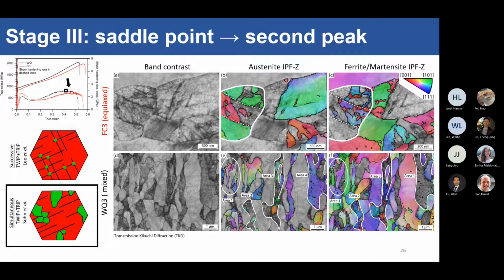So now let's take a look at the martensite. So this was the same sample at the second peak. But now this time using TKD to examine the microstructure. So in the FC steel, I've highlighted here this prior austenite grain with this annealing twin going across. And you can see that the martensite here actually nucleates off the grain boundary and then slowly grows its way into the grain interior. All right, so this is the hallmark of the simultaneous TWIP plus TRIP. Can you see that you've got martensite growing off the grain boundary and then they work their way in?